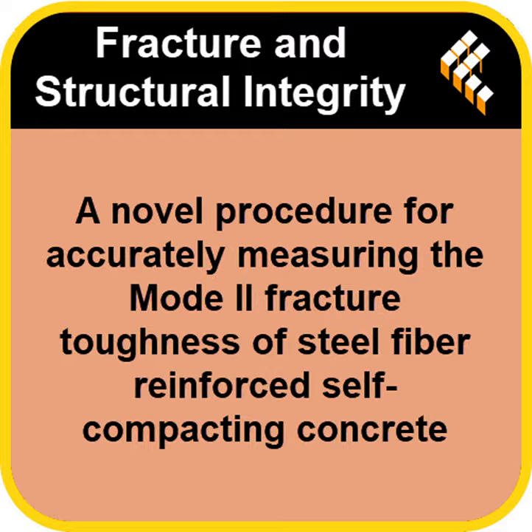Okay, now the really interesting ones. Series 3 was, I thought, particularly smart. They called it MCC, matrix crack-crack. Here, they only put fibers right along the surfaces of the intended crack. The rest of the cube was plain SCC. So that isolates just the bridging effect. Precisely. It tells you how much strength comes only from fibers spanning the gap without any contribution from fibers elsewhere in the material.